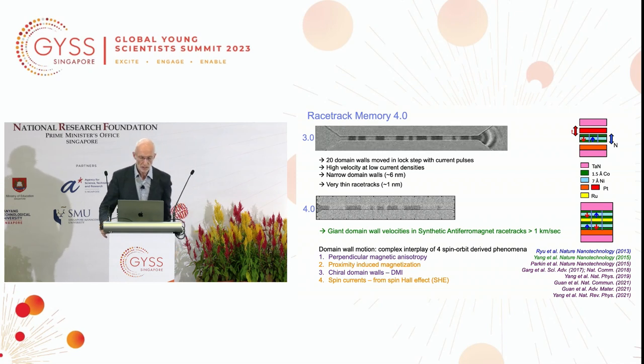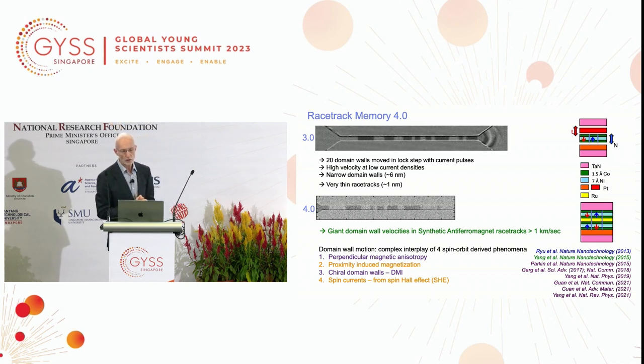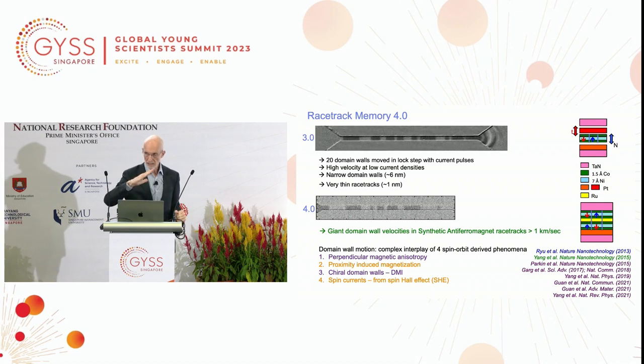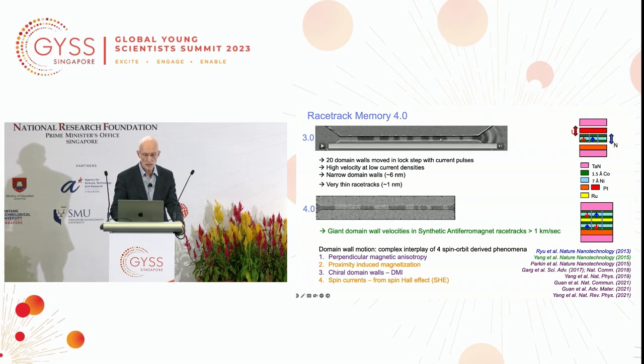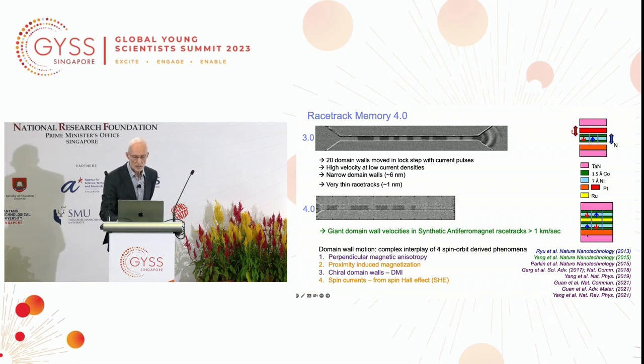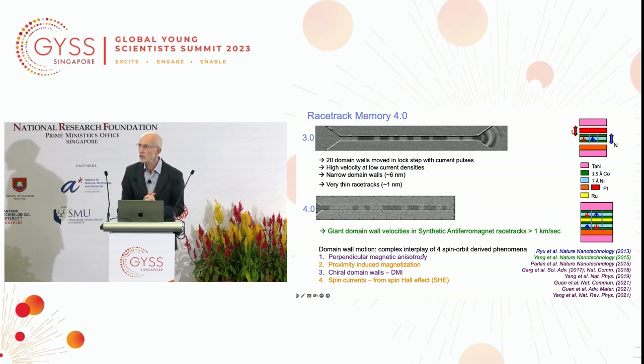So when I was at IBM, we did this by microscopy, so-called Kerr microscopy. You shine a light which is polarized in one direction, and when it's reflected from a magnetic material, the plane of polarization slightly rotates to the right or to the left, depending upon the direction of the magnetic moment in this racetrack. We take a snapshot, and then we apply a current pulse, and then we take another snapshot, and we can see then 20 domain walls you see here moving backwards and forwards in a regular racetrack, a single ferromagnetic layer. Underneath, here's a cartoon of this synthetic antiferromagnet. We have this platinum layer, we have these 1 nanometer thick cobalt, nickel, cobalt, ruthenium, 7 angstroms thick, cobalt, nickel, cobalt, and this has no net magnetization, so it's more difficult to image. These domain walls here are moving much faster.